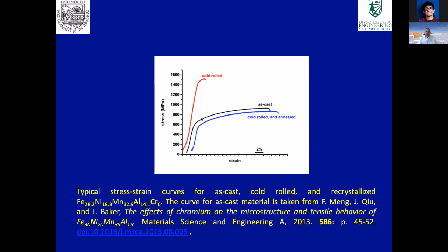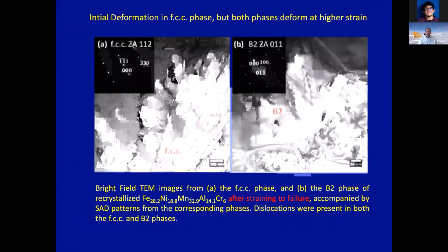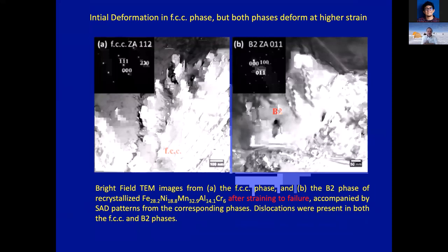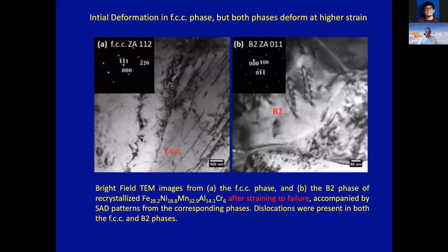And the reason for that is that although we've formed a different microstructure, the spacing of the lamellae in the as-cast material was about the same as the grain size in the recrystallized microstructure. So we get the same strength effect. And when we could get to higher strains in this material with the chromium, what we found was that although we get initial deformation in the FCC phase, later on we get deformation in the B2 phase as well. So the way this material deforms is initially the FCC phase, which is much softer, deforms. And as the FCC phase work hardens, eventually the flow stress in the FCC phase equals the yield strength in the B2 phase, at which point the B2 phase also starts to deform.